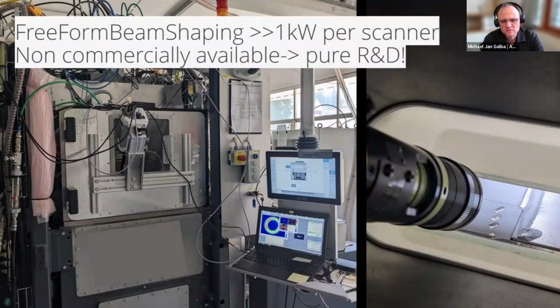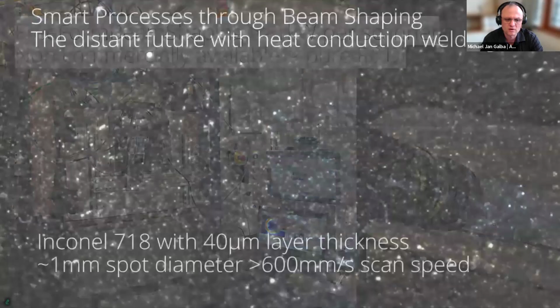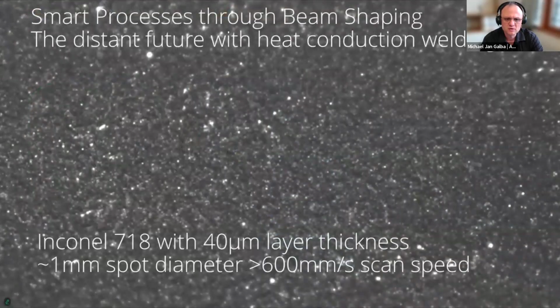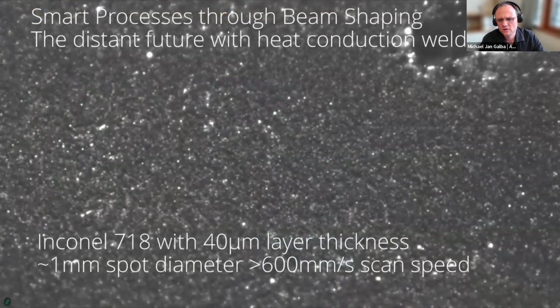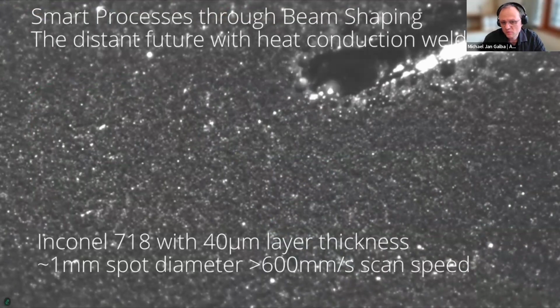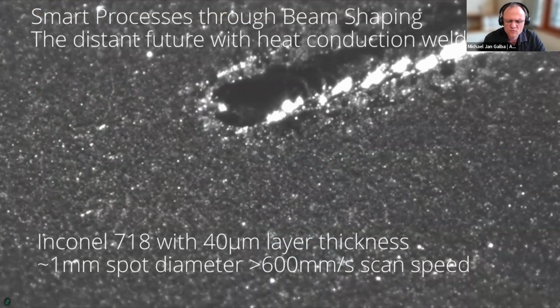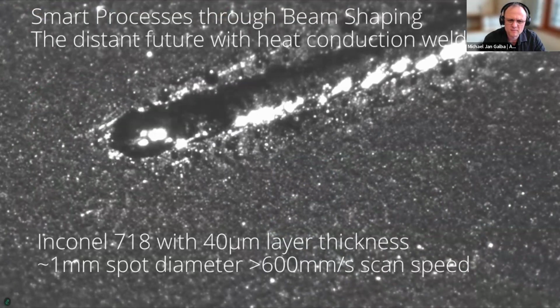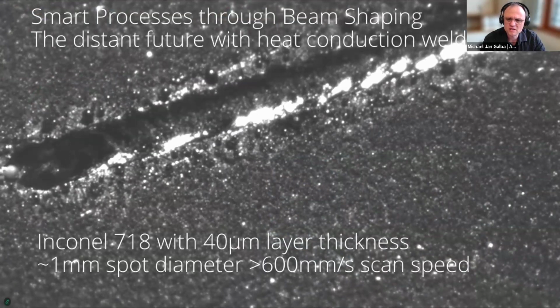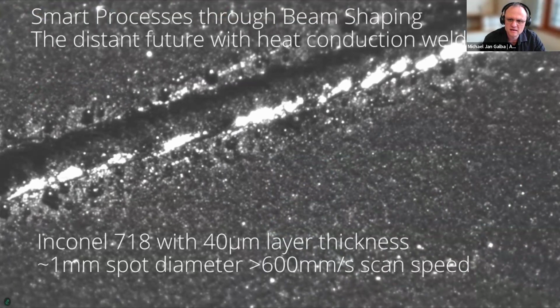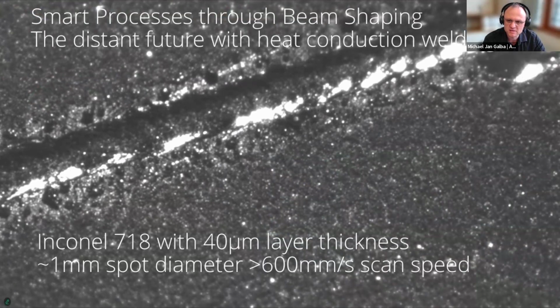It's a scientific machine with a high-speed recording camera here that can take up to 2,000 pictures per second of a small envelope, and that teaches us how the energy source interacts with the powder. So what's brought here is an experiment that we've conducted quite a while ago. It has also been published on LinkedIn already, I think it's 3 years ago, where we have demonstrated that we do heat conduction welding at really high scan speeds with 1 millimeter spot diameters.